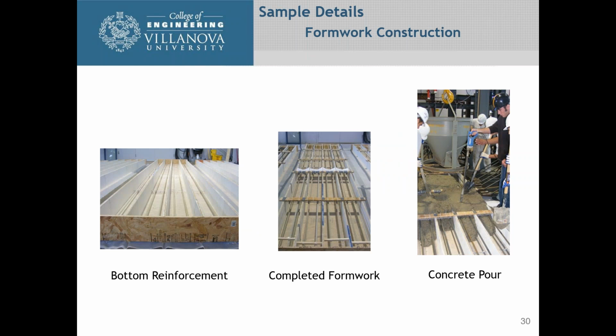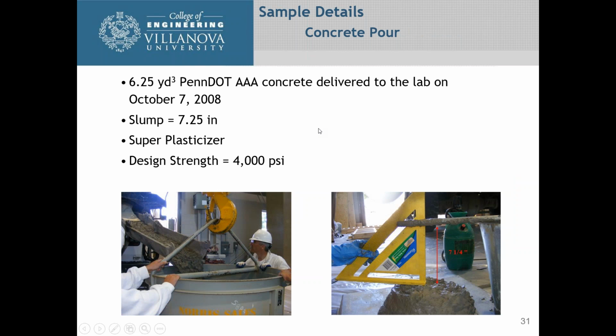So first thing everyone in the lab did is we made up the forms, put the GFRP bars in, poured the concrete, and let the concrete beams cure. We based everything on a PennDOT AAA concrete mix that was delivered to the lab. We had a slump of 7.25 inches, and they added plasticizer in it to help it move around. The design strength that we were shooting for was 4,000 psi.